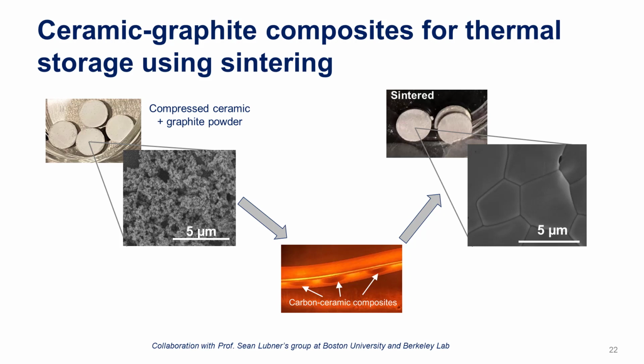So here's those pellets, which are sandwiched between two carbon heaters or two carbon strips. We pass electricity through the carbon strips. It joule heats to a temperature of about 1800 degrees Celsius, which then allows us to sinter these composites. And now this is what the grain structure of the sintered composite looks like. So we've significantly densified these pellets, and you can see these nice necks that have formed between these individual particles.